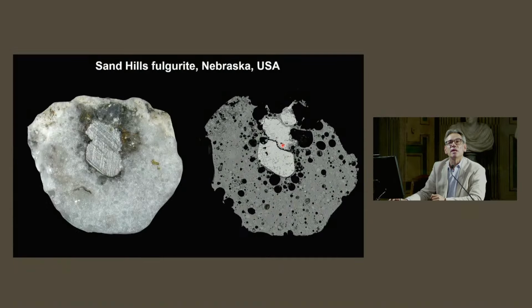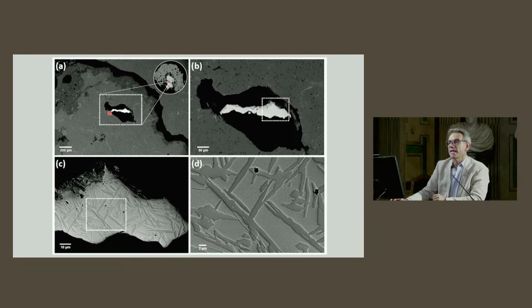But if you look inside one of these holes, or the portion of the metal conductor, look at this - I will show you a blow up in the next slide. It is actually very interesting. This is a portion, look at this, and a blow up here, and again here and here. It is actually composed of two phases and a circular grain in a matrix. So we decided to use FIB, focused ion beam, to take two FIB lamellae to study by transmission electron microscope.